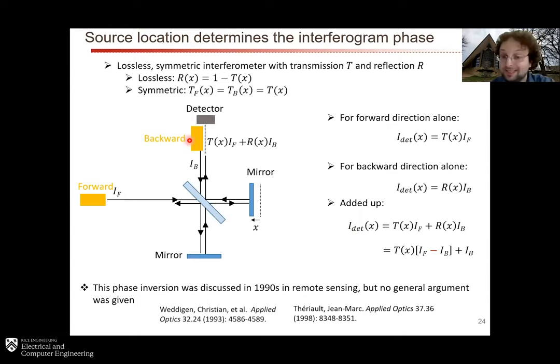very, very similar intensities. And of course, when your sample is at low temperatures, for example, 30 degrees, 20 degrees, and your entire instrument is close to room temperature, even you, the person standing next to the instrument, is close to room temperature, a little bit higher, you can very easily get this kind of cancellation effect. And so you just have to be able to take it into account and be able to predict when it's going to happen in order to understand your thermal emission measurements.